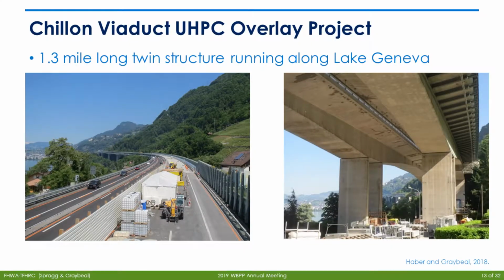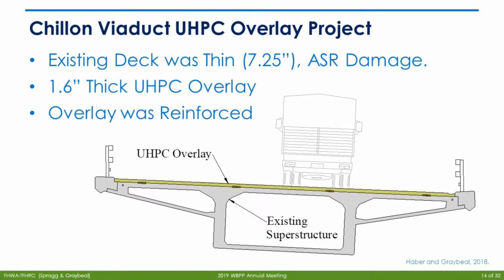The Chillon Viaduct is a bridge in Switzerland. Here's some photos of what that might look like. Here is the existing structure. You can kind of see that it looks very slender, I think. I saw it and I was like, wow, I'm kind of glad I don't drive in Switzerland. So they were putting a 1.5 inch or 1.6 inch UHPC overlay on the top. So this particular application was not necessarily looking at rehabilitation, but they were also including some strengthening along with that. They did some calculations, and the primary goal was to increase the structural capacity of this bridge. But it gives us a nice example of what this would look like if we were to implement this in the United States on a big structure.